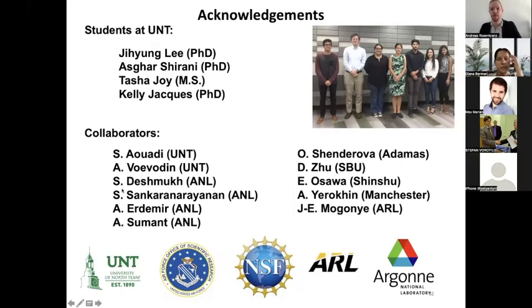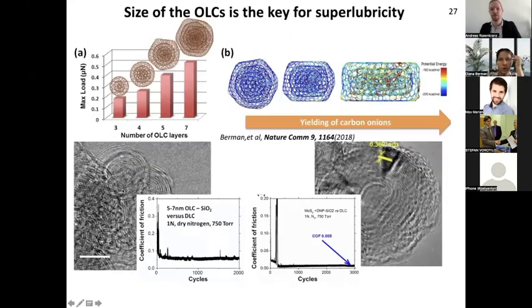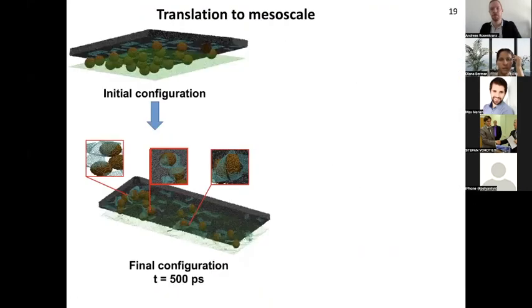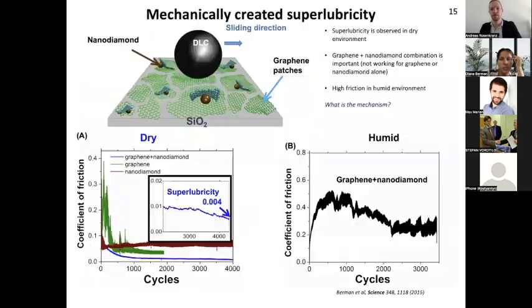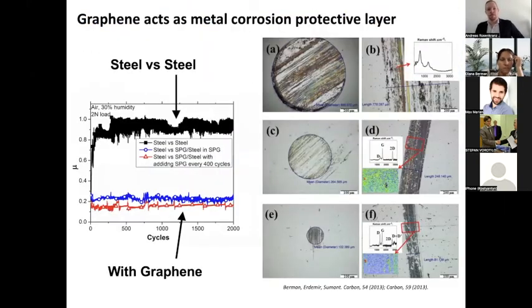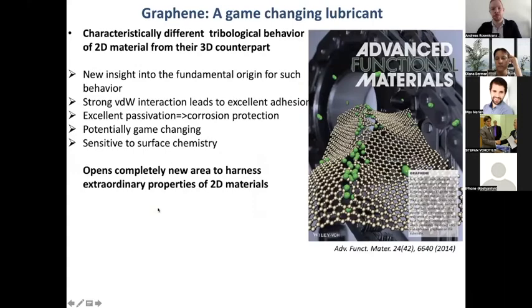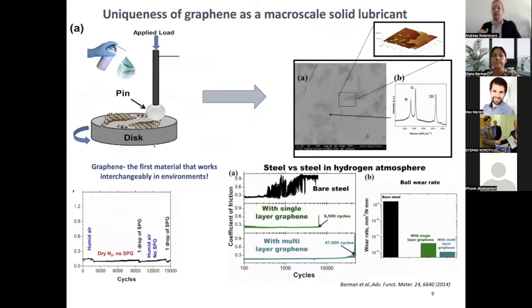So those spikes which were observed in some of the graphene sliding, you see some here, the spikes, this is actually originating due to the addition of ethanol and how quickly it evaporates from the surface. Right. Yeah, ethanol is mostly a very nice compromise of a simple solvent for this kind of process. Yes, ethanol is the best, and it's pretty safe.